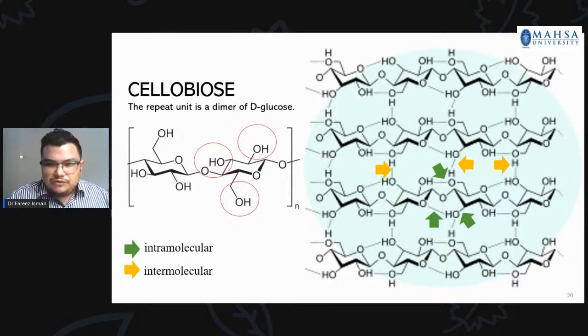So these elementary fibrils will be bundled together to produce microfibers, which then form cellulosic fibers. And one of the most distinguishing and useful characteristics of cellulose is the high degree of hydroxylation along the polymer chain, and each monomer contains three hydroxyl groups.